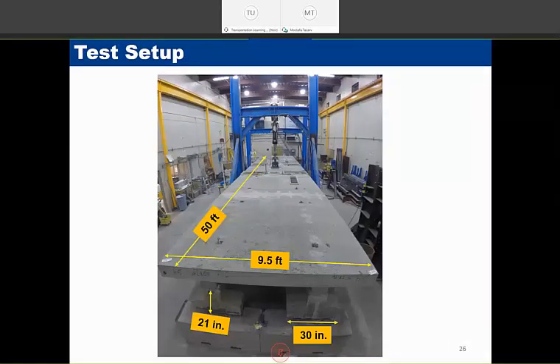This photo shows the test setup for the precast bridge. You can see the actuator, the hydraulic jack at the middle of the bridge. This test setup was used for the fatigue testing. We also adapted it for the other types of testing just to make sure that the bridge is tested for the worst case scenarios. And as I said, we were limited to a 9.5 feet wide bridge because of the test setup limitations we had here.